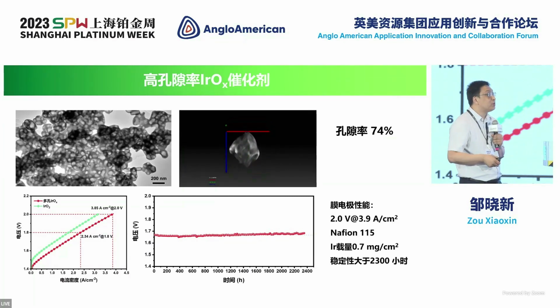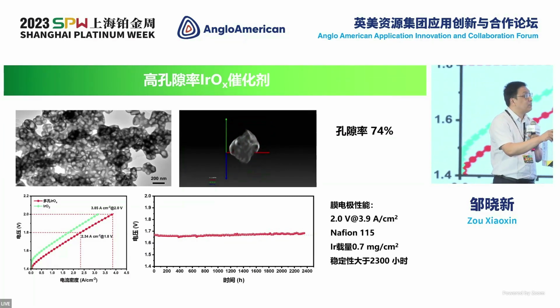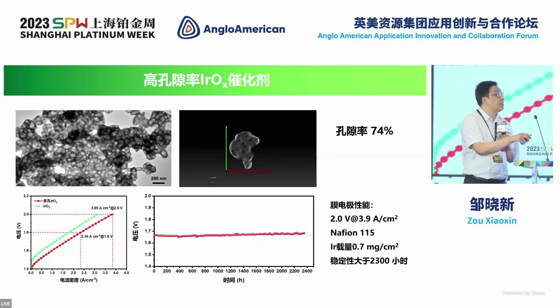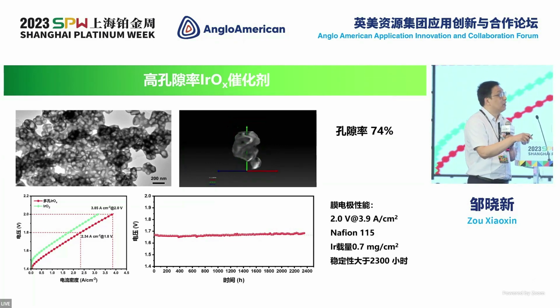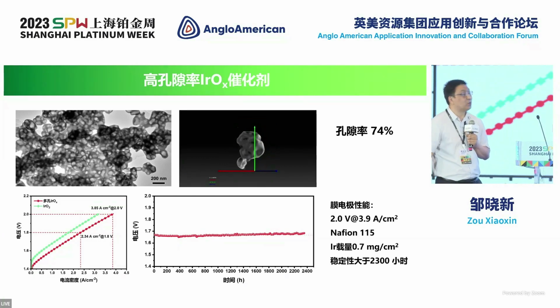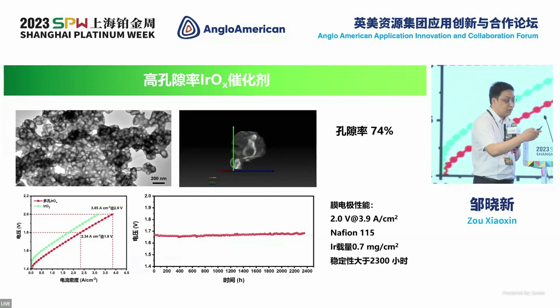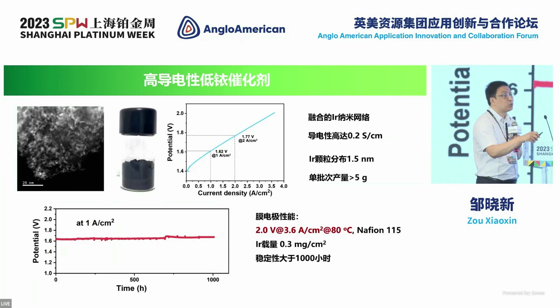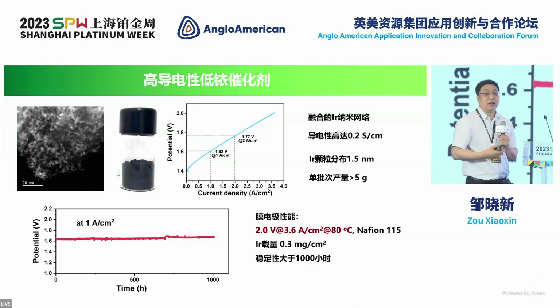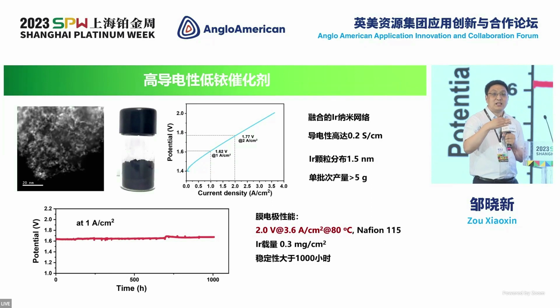It is highly porous, a structure with a large content of cavities. With this structure, we can improve its activity, reduce its loading, and improve the stability. So far, we have tested over 2,300 hours, and it performs well. So apart from iridium black and iridium dioxide, there are other possibilities.